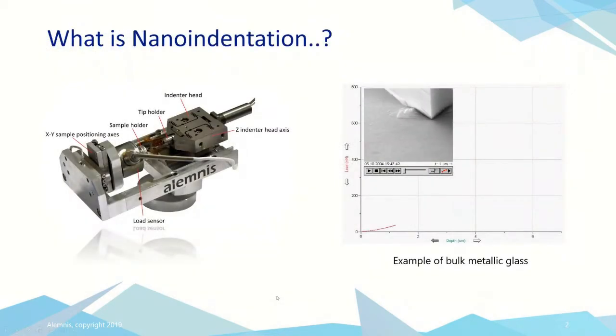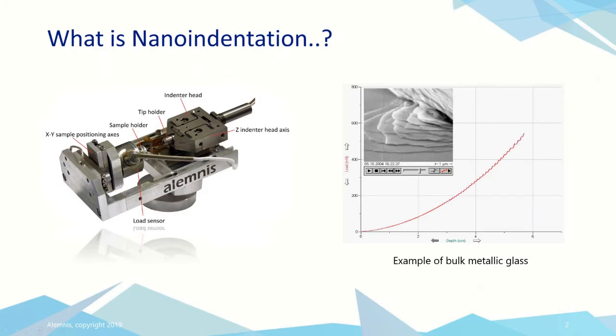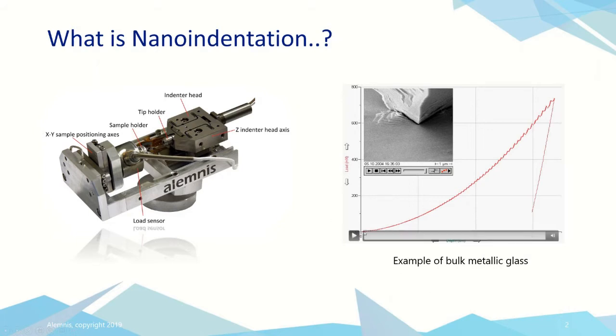Here we can see a basic Alemnis system, and we can see an example of a typical nanoindentation. You can see that when we're indenting, we're using an indenter of known geometry, and we're indenting the sample either under load control or under displacement control. Now the system works using an actuator here on the right where the indenter is placed, and the sample is mounted on an SEM stub here on the load cell. It's a little bit different when we optimize this system into the NenoVision LiteScope, which you'll see in a little while. Now, the resultant test, we basically generate a load displacement curve.